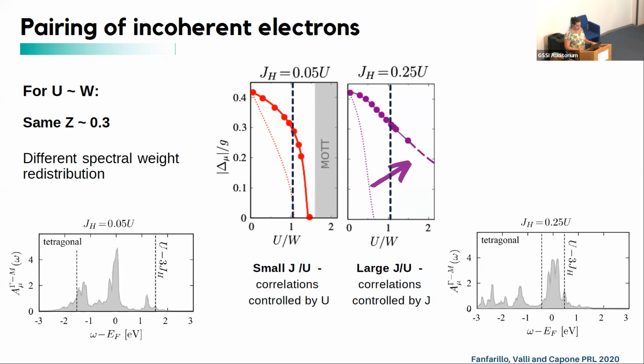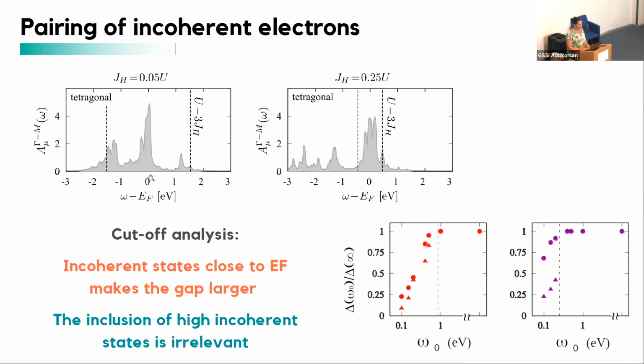And I can probe the result better if I start to restrict the BCS integral. I'm moving the cutoff from infinity to closer energy. I'm plotting here the delta that I obtained with the cutoff at infinity versus the delta obtained with the moving cutoff. And you see that the result is stable until 1 electron volt. So it means that integrating over these states beyond 1 electron volt is completely irrelevant. It's not changing the value of the gap. But when you are accounting for this incoherent weight, the gap is actually changing.